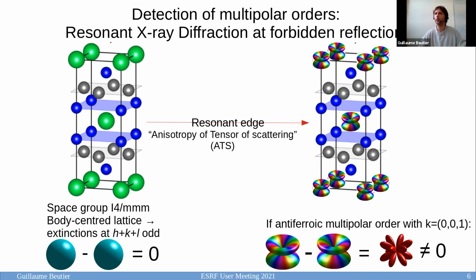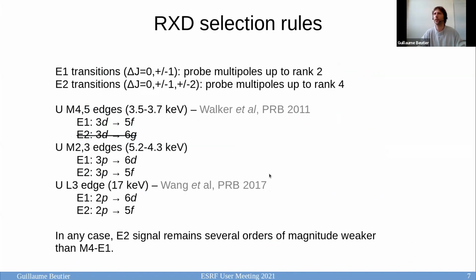And the reason why is that when you use resonant X-ray scattering, you are enhancing your sensitivity to the anisotropy of the tensor of scattering. That means that when you're non-resonant, you essentially see a spherical charge distribution, whereas when you are resonant, you can see anisotropic distribution of the valence shell. And if your corner and the body center sites have, let's say, different anisotropies, you would end up with something at these forbidden reflections. But this is fairly weak, and of course it depends on the edges that you are using.